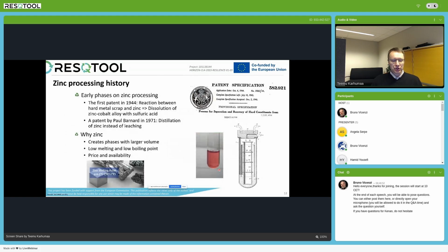Then I would like to touch a little bit on the zinc processing history. The earliest patent or publication on zinc processing comes from the year 1944, where a company in the UK described how, when hard metal scrap and zinc were put in an oven together, a zinc cobalt alloy formed, and then they described how this alloy of zinc and cobalt can be dissolved with sulfuric acid, and the remaining tungsten carbide can be recovered and used in the production of new tools. This process was not utilized on a very large scale, only after Paul Barnard in 1971 patented a process continuation for this. So the distillation of the zinc instead of leaching improved the process a lot, and then that process started to gain market share.